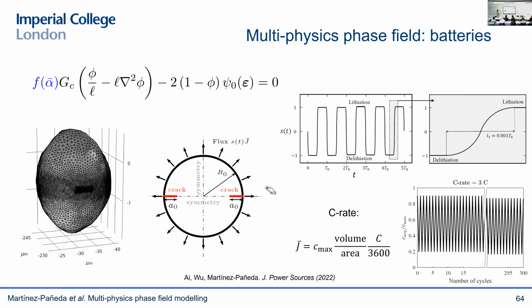A few people have done this before. They have looked into phase-field models for electrode particle cracking, but they were only looking at one half cycle. But this is a cyclic process. So we added the fatigue contribution here, and we subjected this electrode to a sufficient number of cycles. Relevant to electric vehicles, we're talking about a few hundreds of cycles. And we looked not only at idealized particles, but also realistic particles that we can measure from X-ray CT scanning.